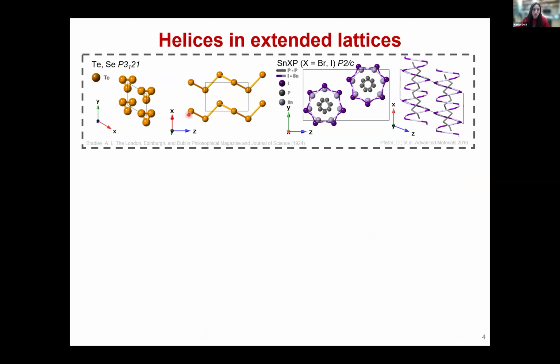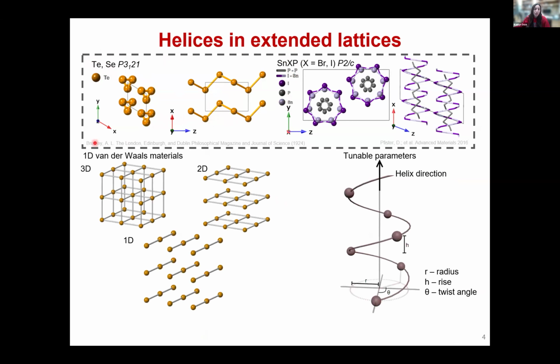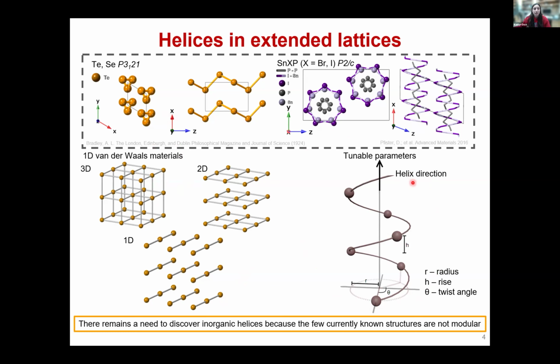These are basically the only two known classes of helical freestanding inorganic solids. One is based on crystalline tellurium, the element, and the other is the structure tin iodophosphide. These materials are both 1D van der Waals materials, meaning that they can be exfoliated into few nanowire thick chains or even into single chain materials pretty easily while retaining their crystallinity and long range order. They also have an indexable set of tunable helical parameters that can be used to directly modulate the chirality-induced spin selectivity effects. However, neither of these materials are very modular. Only one structural analog exists for each.